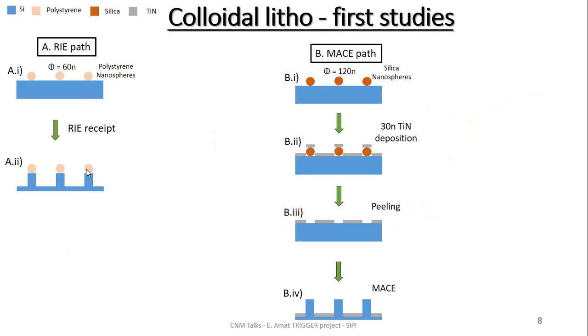Also, we have made the first studies on colloidal lithography. These are the first studies. I remember two paths to analyze, to make experimental work. One based on reactive ion etching and the other based on MACE. For the reactive ion etching, we are using polystyrene nanospheres with a 60 nanometer diameter. With this approach, we only have to deposit these nanoparticles, and then by reactive ion etching, we will achieve the pillars. It's more direct, it's easier. And for the MACE path, we are using silica nanospheres, 120 nanometers in diameter.